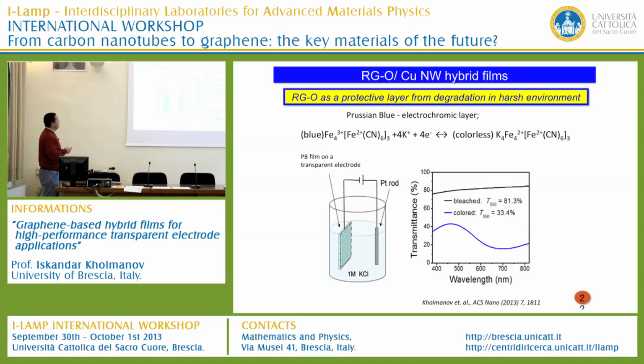So here we used reduced graphene oxide, copper nanowire hybrid films as a transparent conductive electrode in an electrochromic device. Prussian blue film was used as the electrochromic material, as the electrochromic layer. The Prussian blue optical properties can be reversibly modulated from the bleached state to the colored state.